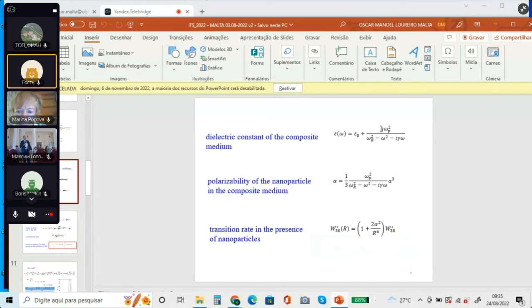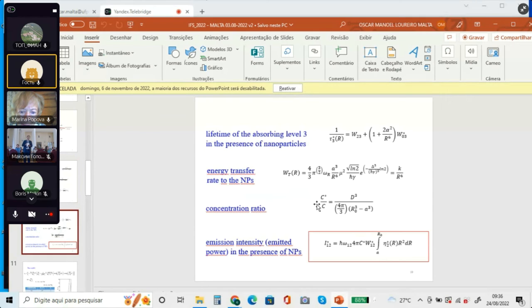Yes, it's here. You see the first equation of the dielectric constant. The concentration is taken into account through this factor Q, which is called the filling factor. Okay, so the concentration is there, but it's an important point. We have to be very careful because since we put nanoparticles, the concentration will be changed, okay?